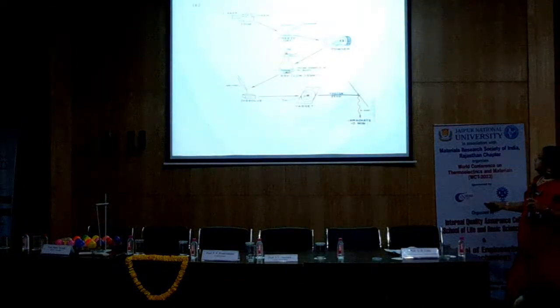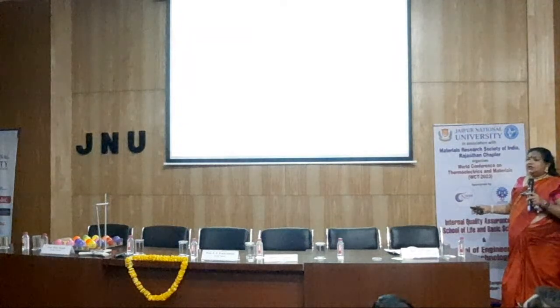So I just wanted to add sample preparation. Now, I would show you the X-ray absorption cross-sections of these two techniques. XRF is connected with photons, and PIXE is protons, proton-induced X-ray emission. PIXE is good for the low Z elements because the cross sections are higher. I'll show you the graph. I don't know if I have brought it. And for photons, XRF is for the high Z, the rare earth elements, if you know the periodic table.